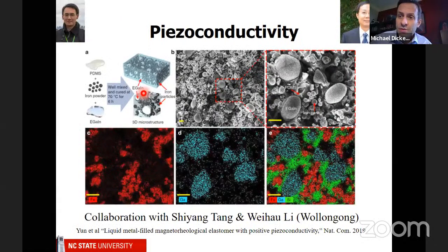So speaking of piezo properties, I was really lucky to be part of this collaboration that discovered something that I think is pretty exciting. In the previous work, we mixed liquid metal with silicone. But here we are mixing it also with solid magnetic powder. So this is what it looks like. If you look under a microscope, it looks kind of like a mess. It's got these liquid metal particles, iron particles. And if you look at the elemental composition, you can see the iron and the gallium, they're all mixed together.